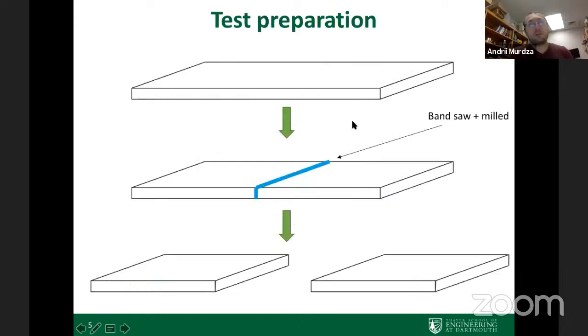So how did we prepare the test? First we milled the specimen, the ice plate. Then we cut it with the band saw, and in most of the test cases we milled this cut surface, such that we received two parts of this ice plate, and these parts would later be brought together in contact.